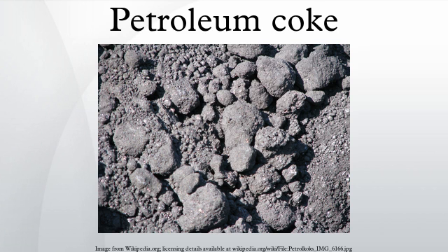Catalyst coke is coke that has deposited on the catalysts used in oil refining, such as those in a fluid catalytic cracker. This coke is impure and is only used for fuel. Fuel grade coke is classified as either sponge coke or shot coke morphology. While oil refiners have been producing coke for well over 100 years, the mechanisms that cause sponge coke or shot coke to form are not well understood and cannot be accurately predicted. In general, lower temperatures and higher pressures promote sponge coke formation. Additionally, the amount of heptane insolubles present, and the fraction of light components in the coker feed contribute.